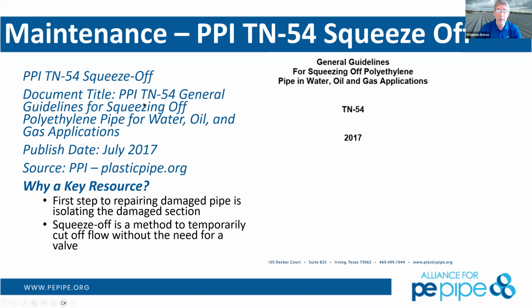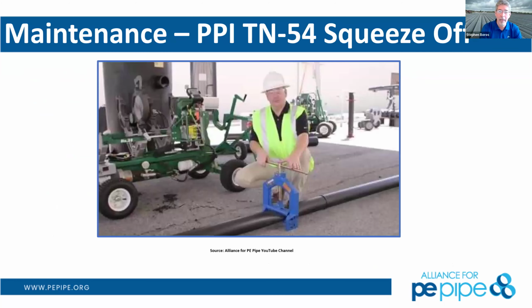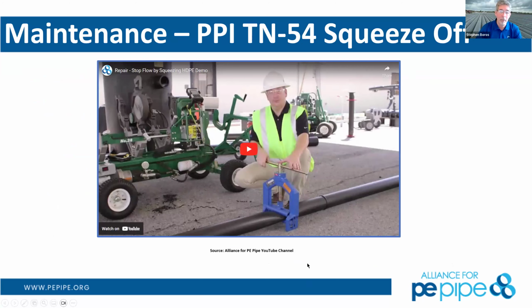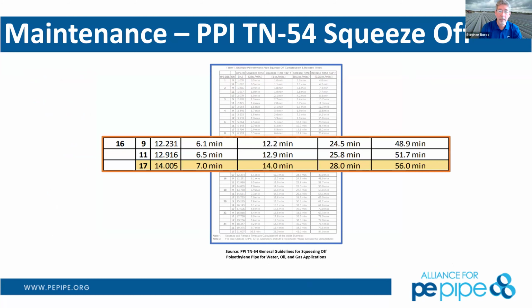And there's a guide for this, PPI TN-54, General Guidelines for Squeeze-Off of Polyethylene Pipe for Water, Oil, and Gas Applications. This is going to be different from gas distribution applications, which have some different caveats in them. But if you go through this methodology, it will make sure the pipe is not damaged. I'm not going to play the video here because it takes a while, but this is essentially what a squeeze-off tool looks like. It's a barred tool, barred on top and bottom with a very specifically designed radius. Then you squeeze off at a very specific squeeze rate, do your repair, and then you release that squeeze again at a very specific rate. That's going to be key in this process.